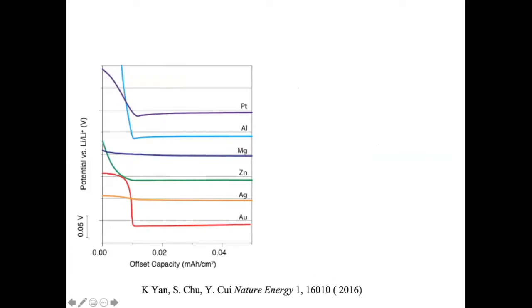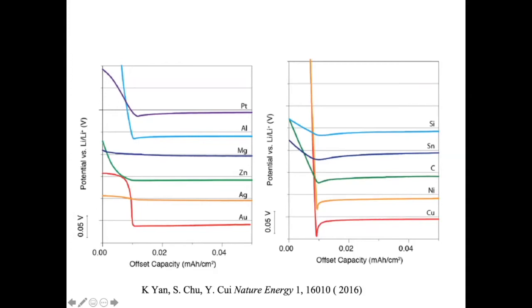With this exciting initial discovery, actually we screened a number of different substrates, from gold, silver, zinc, magnesium, right? You see this, we shift the voltage curve. You look at this, you say, well, for all these substrates, they don't have nucleation barriers right there. You go look at the phase diagram between these metals and lithium. It fits, our explanation really fits. And then you look at copper, nickel, and carbon, it always has some nucleation barrier, seeing this voltage dip right there.